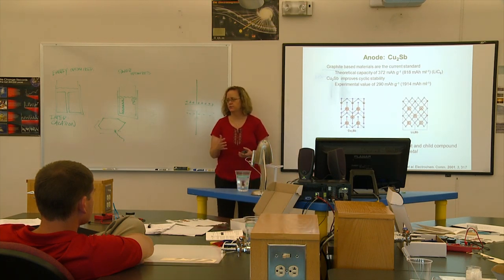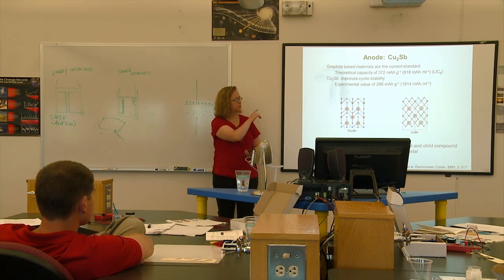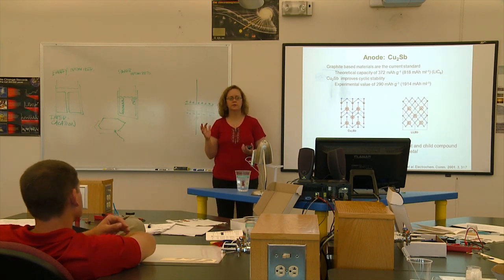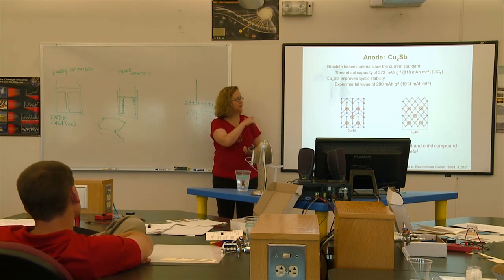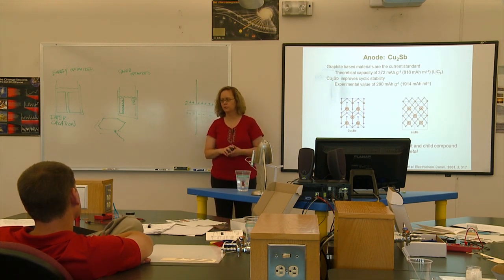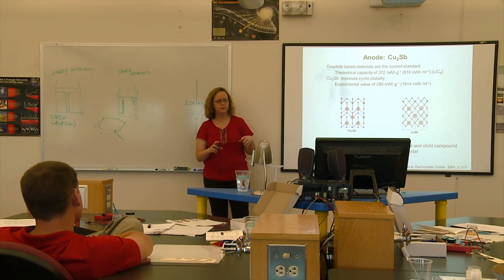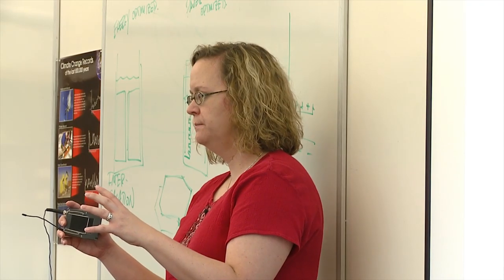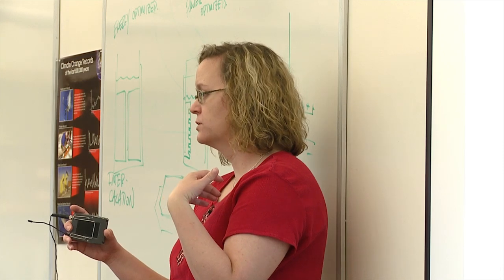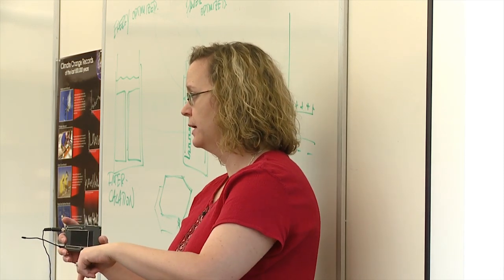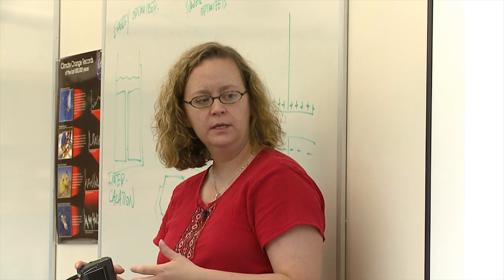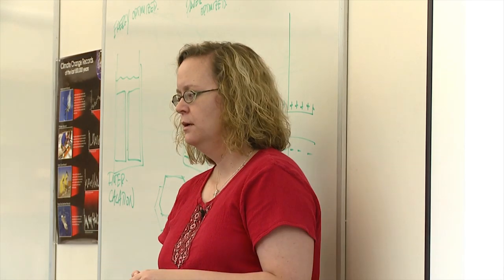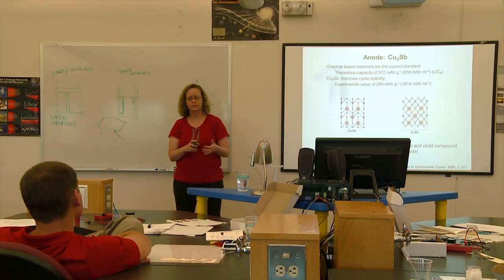Most of these kinds of compounds have enormous volume expansions, and so they pulverize so fast that you can't really use them. There are companies now trying to use silicon instead of carbon, and that's a similar kind of idea. Silicon has a 300% volume expansion when you put lithium into it. Copper antimonide is only about 75%, so it's a lot lower. And the reason it works is because the antimony atoms basically don't move. They make kind of a skeleton. The lithium goes in, the copper comes out, and then it's reversible. When you take the lithium out, the copper goes back in, and that's how you cycle it. What's really important is that it lithiates about 50 millivolts more positive than the plating of lithium metal.